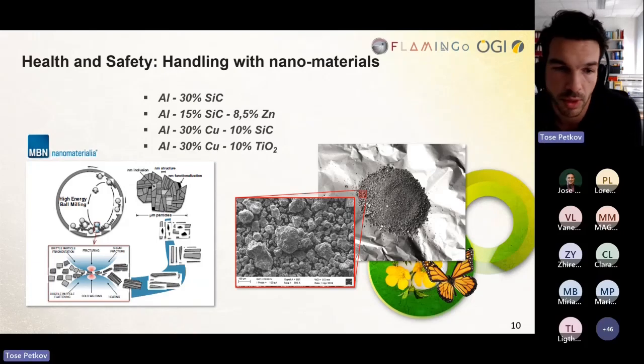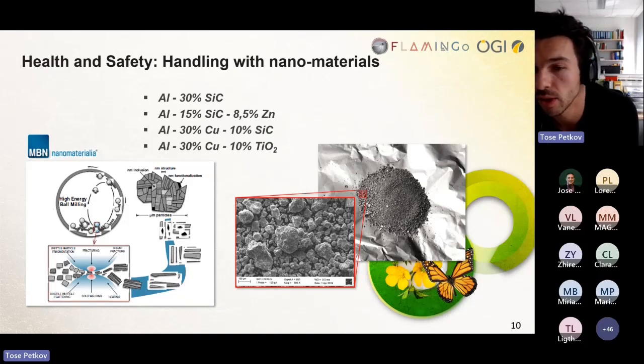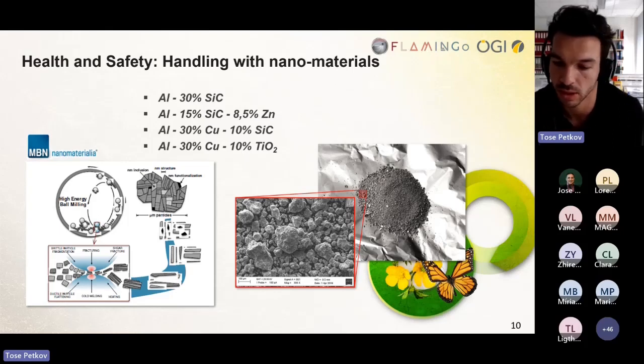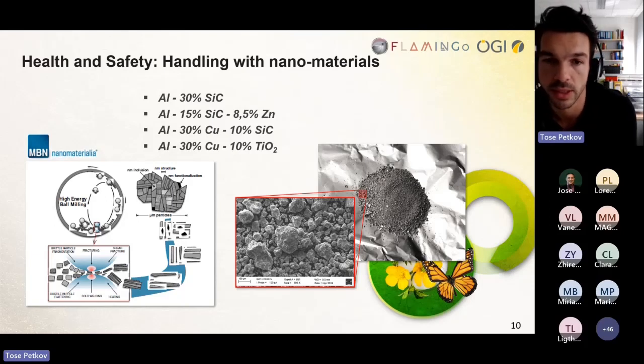The good thing is that after this production, you have a powder in a scale of about 100 to 200 micrometers, which is easy to work with.